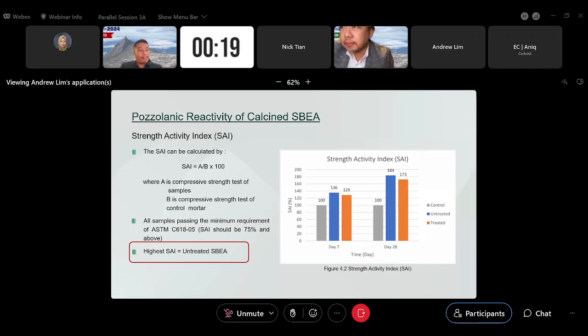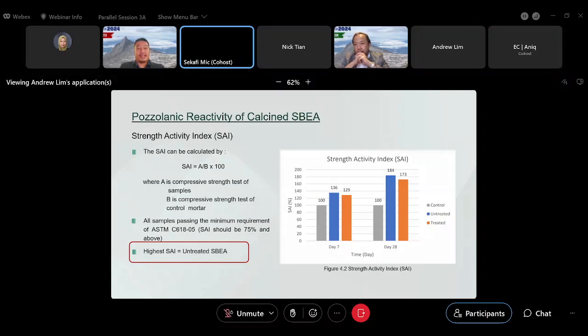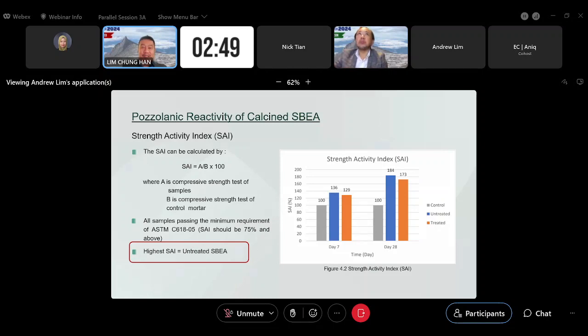I'm Nelly. I just want to ask, regarding the SAI, is there a reason why the untreated SBA is higher than the treated SBA? So in this instance, the untreated SBEA has a higher strength, and the treated one lower strength, because there is research out there that indicates this, and the way I do the treatment is using calcination. Calcination means you subject the pozzolan to high temperatures before you actually use it as a pozzolan. So that's the treatment I'm using.